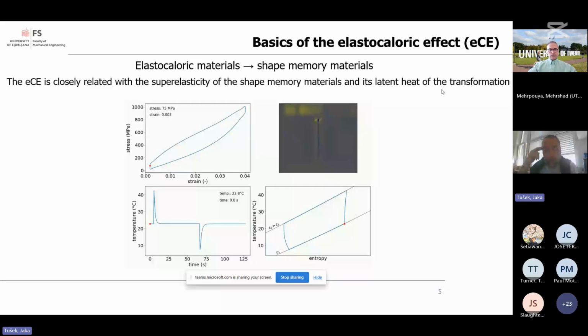The elastocaloric effect itself is closely related to the superelasticity of shape memory materials and its latent heat during the transformation. So this stress-induced martensitic transformation is an exothermic and endothermic transformation, which causes latent heat release, and absorption of the latent heat during reverse transformation. So essentially, all shape memory materials can be considered as potential elastocaloric materials.